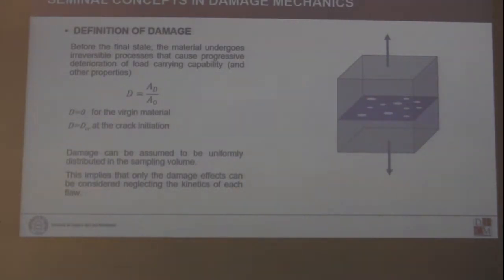And the way we define the damage in this way gives us the possibility to deal with a theoretical or virtual material in which we define not the kinetics of the evolution of each single isolated damage mechanism, but we capture damage in terms of the effect that the damage state has on the material properties. This is a really turning point because we detach from the physical description of the damage ongoing in the material, and we describe that damage state, which can be as complex as we want, as the sum of the effects that reduce the material load carrying capabilities.